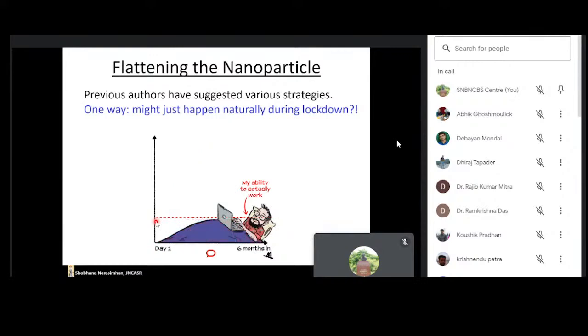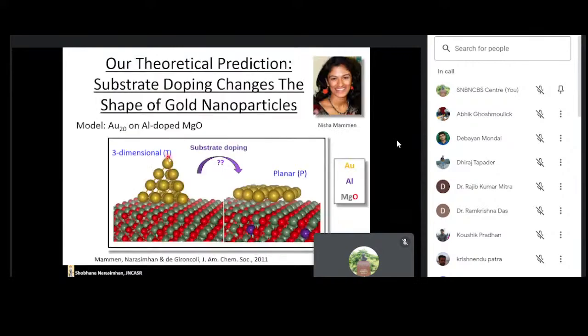Okay. So what we thought of was that if you have this three-dimensional nanoparticle, which is supported on an oxide support, and you dope this support, that is, you take some of these gray divalent magnesium atoms and replace them with these purple trivalent aluminum atoms, then there are electrons floating around because of the aliovalent doping, and these electrons may get transferred to the nanoparticle and end up flattening it.